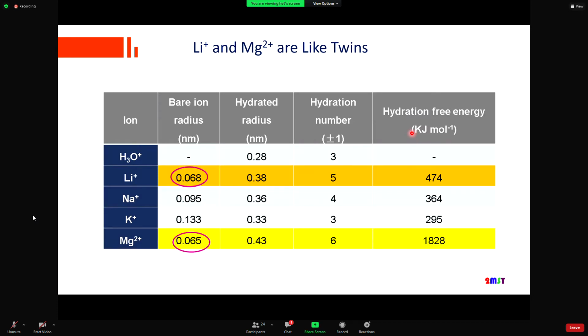For separation, the second constraint is the separation of lithium and magnesium. The bare ion radius of lithium and magnesium are very close, even hydrated radius. The only large difference comes from hydration-free energy. This gives us a hint that we might not be able to use diffusion-controlled separation technologies, and should instead use affinity-controlled separation technology to achieve very high separation for magnesium and lithium.